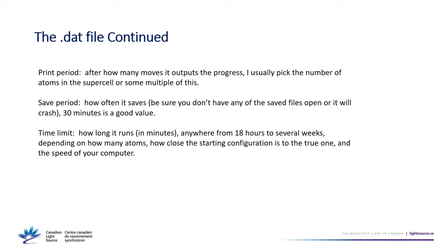So this you need to run it pretty long, and this depends on several things, like the speed of your computer, of course, also how many atoms you have, how close to the starting configuration the actual configuration is. So I would usually start it at like one day and then come back and look at it the next morning, so run it almost a full day. Sometimes for more complicated things, you may need to run it several days or even several weeks. And there's a paper at the end that I'm going to recommend you guys look at that talks about that. I found it very interesting.